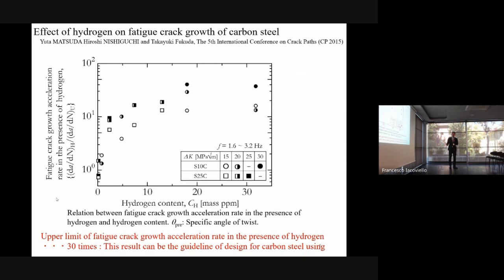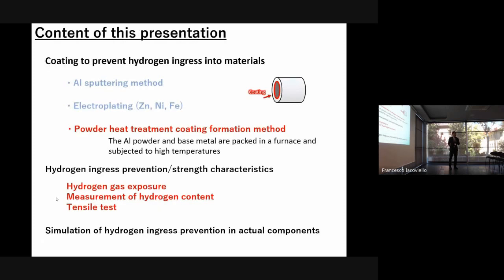Then this graph shows the relationship between hydrogen content and fatigue crack growth acceleration by the hydrogen. The fatigue crack growth acceleration increases with the increase in hydrogen content like this. But I thought that the graph would be like this, but there is an upper limit. If the hydrogen content is too much, the upper limit is 30 times. This graph explains to us, don't worry about hydrogen embrittlement too much. This result can be the guideline of design for carbon steel using. But anyway, we must prevent hydrogen embrittlement.